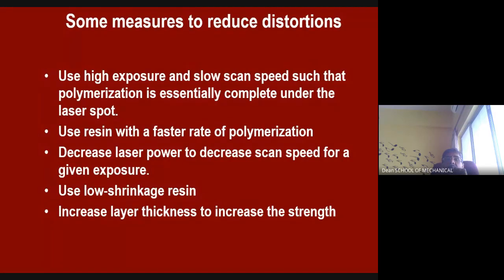Some measures to reduce the distortions. Use high exposure and slow scan speed such that the polymerization is essentially complete under the laser spot. Use resin with faster rate of polymerization. Decrease the laser power to decrease the scan speed for a given exposure. Use low-shrinkage resin. Increase the layer thickness to increase the strength. These are all some measures to reduce the distortion during the process.